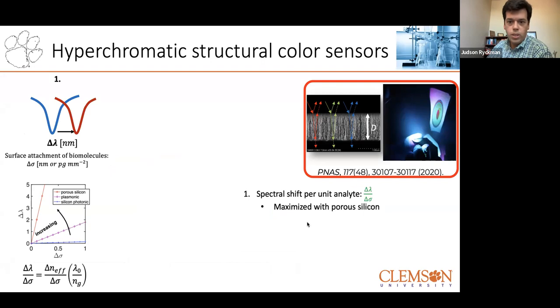Well, one, porous silicon is widely used in the biosensing community because it has one of the highest sensitivities. That is the spectral shift that you can obtain, the delta lambda, per unit of, say, small molecules either bound to the surface in some equivalent add layer thickness, like a 1 nanometer monolayer, or some mass surface density, say picograms per millimeter squared of molecules, will provide a very high wavelength shift. And that's really because the effective refractive index, the delta N of the material itself, increases quite a bit thanks to the high surface area and tunable pore size. So this is much better than even a plasmonic or an evanescent, say, silicon photonic resonator type platform. But this is only one piece of the puzzle.